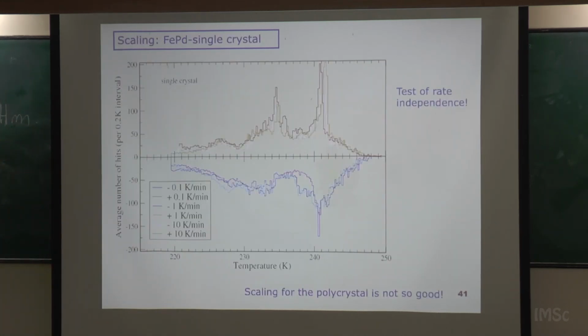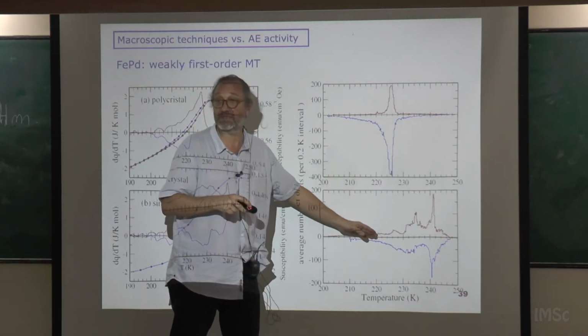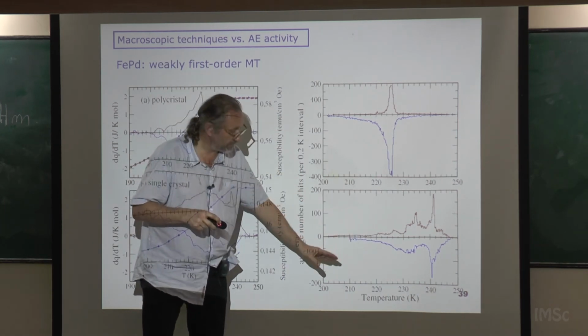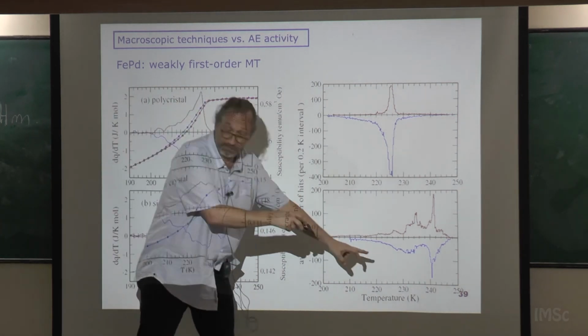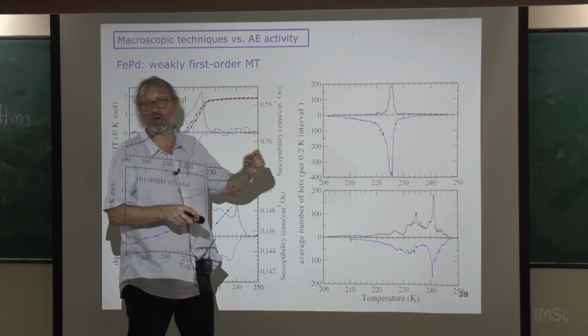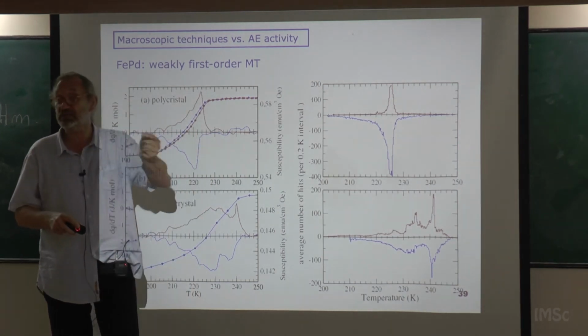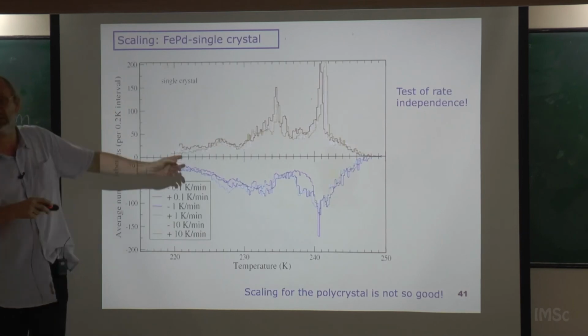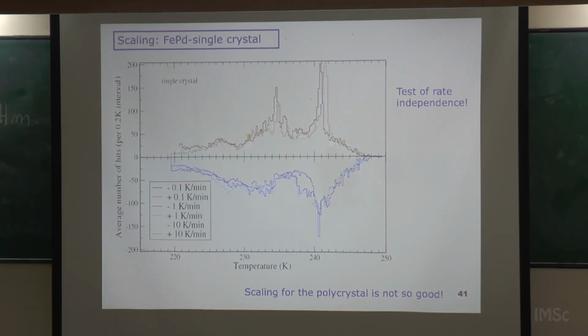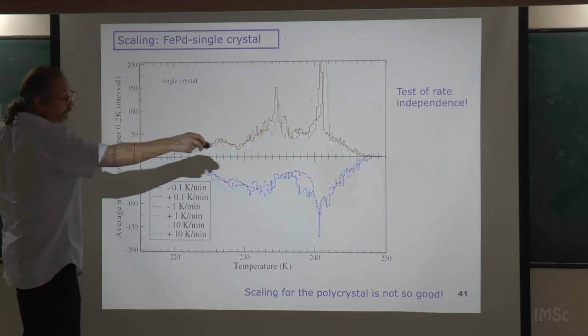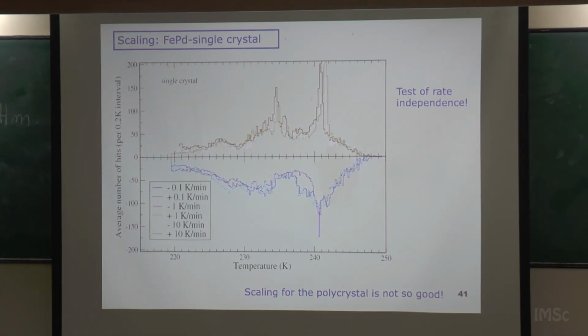Then if you study the distribution, this is just the test of the rate independence of hysteresis. If you plot these curves here, now you change the driving rate, the curve changes, if you plot it as a function of time. But when you plot it as a function of temperature, and here you put not the number of events per time, but the number of events per temperature, the curves overlap. And this is the test of rate-independent hysteresis. At different rates, you get exactly the same curves. If you go slower, then in time, one will expand more or less. But so the problem does not depend on the rate. That is a signature of being athermal, which is the case in these transitions.